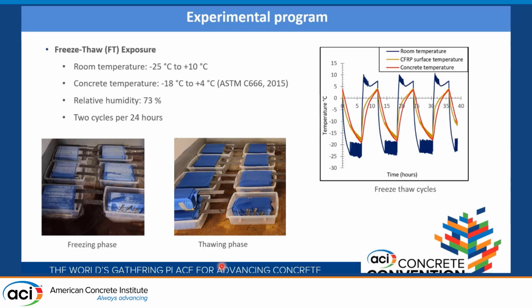Going to present the freeze-thaw exposure: the environmental room temperature was set between minus 25 degrees Celsius and plus 10 degrees Celsius to obtain a temperature range of minus 18 to plus 4 degrees inside the concrete, as recommended by the ASTM standard. To maintain the moisture of the CFRP concrete joints during the freeze-thaw cycles, the samples were covered with water-saturated fabrics. So 2 freeze-thaw cycles per day were performed.